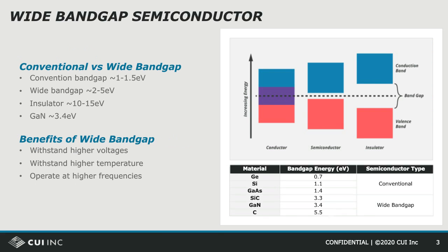There's one more category of materials that GaN belongs to, and that is the class of wide bandgap semiconductors. It's this characteristic that is most valuable to power supply manufacturers. Compared to conventional semiconductors such as silicon, which have bandgaps around one to one-and-a-half electron volts, wide bandgap semiconductors have bandgaps greater than two electron volts. Other wide bandgap materials include silicon carbide and carbon. The bandgap is the energy separation between valence and conduction bands within the material, and a wider bandgap makes something more insulative and capable of withstanding higher voltages. Elevated temperatures will also act to close the gap, so having a wider gap means the material is able to withstand higher temperatures as well. A third benefit is higher electron mobility, which means electrons are able to move through the material faster for the same applied electric field, translating into higher frequency capabilities than conventional semiconductors.